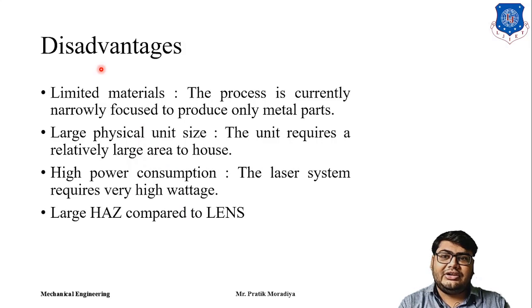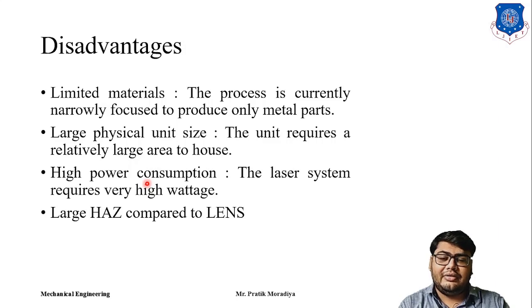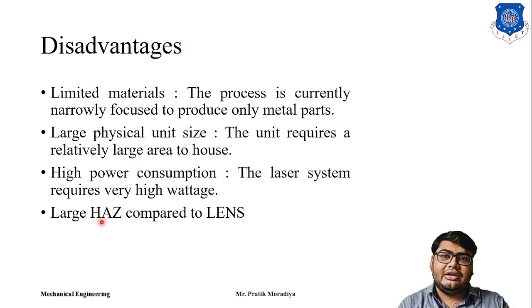The disadvantages of DMD include limited materials — you can only produce metal parts. The physical size of the unit is very large and the power consumption of CO2 lasers is very high. Because CO2 lasers have a higher wavelength than Nd:YAG lasers, they are absorbed less by materials, so you need to provide more power. This results in a higher heat affected zone and higher heat transfer to the platform compared to LENS.